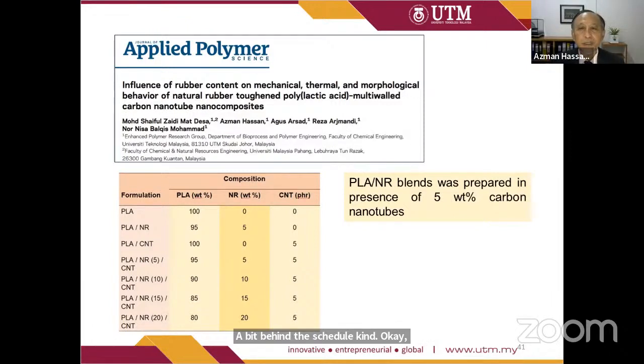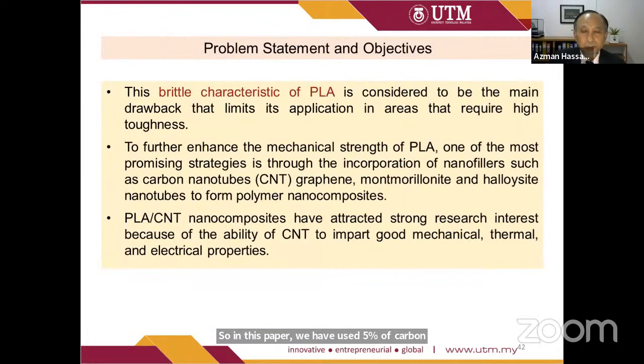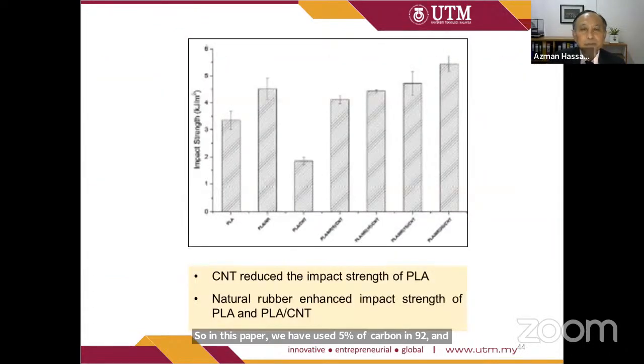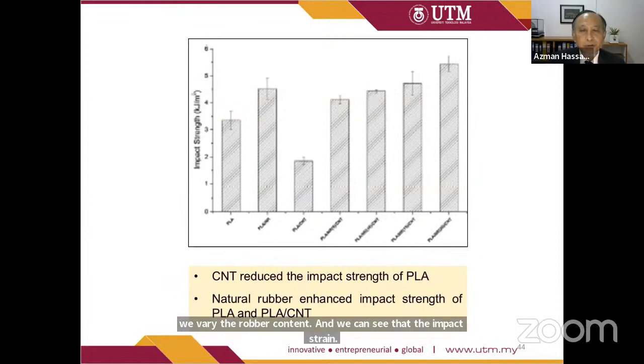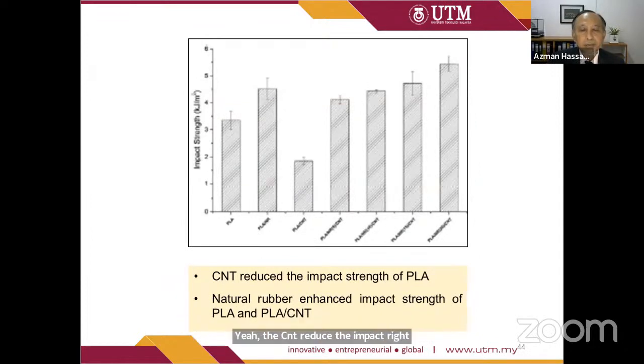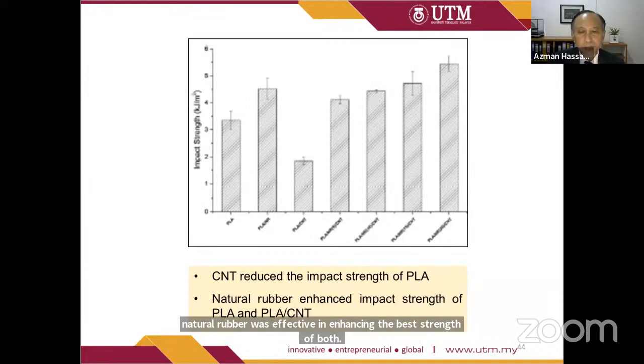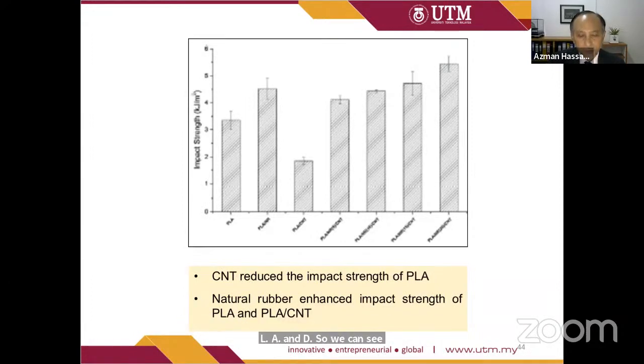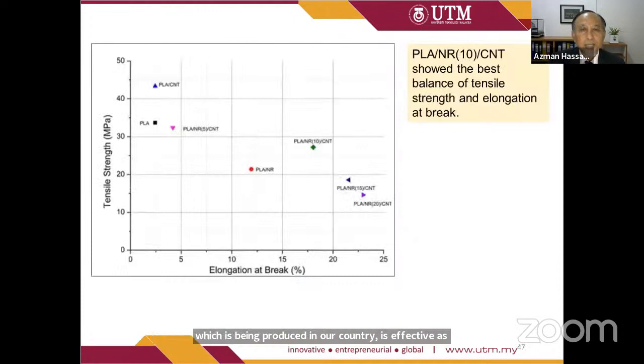So in this paper, we used 5% of carbon nanotube, and we varied the rubber content. And we can see that the CNT reduced the impact strength of PLA, but the natural rubber was effective in enhancing the impact strength of both PLA and PLA/CNT. So we can see that our own natural rubber, which is produced in our country, is effective as an impact modifier for PLA. And we have come up with the most optimum formulation by the use of natural rubber at 10%, which gives balanced properties in terms of tensile strength and elongation at break.